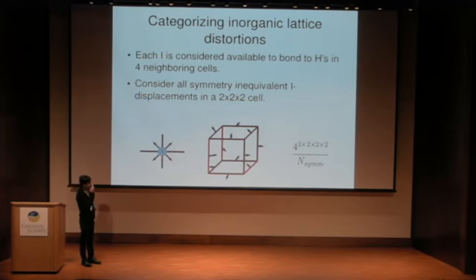Now that I've addressed the hydrogen bonding, next I want to explore the distortions of the inorganic lattice. I can think about this in a simple way. Each iodine atom is surrounded by 4 cells where it can make hydrogen bonds to. So going back to this notation, I can think of a possible inorganic distortion as putting arrows on each of these edges. And each of these arrows can point in one of 4 directions. Now, if I count the total number of possibilities, it's a very big number. Basically, I have 4 possibilities per iodine, and it's a 2 by 2 by 2 cell, and there are 3 iodines per cell. So there are a lot of them, and even accounting for symmetries, there are still very many, but I've tabulated all of them in the database.